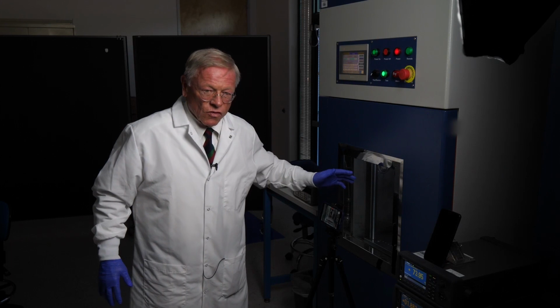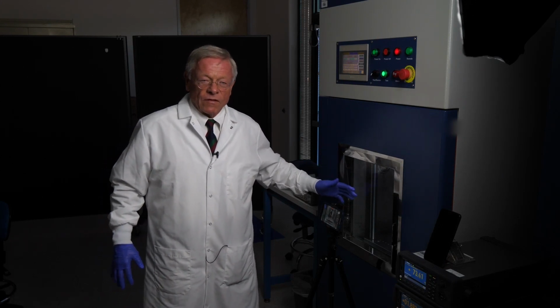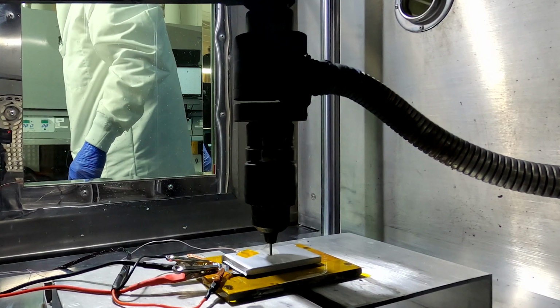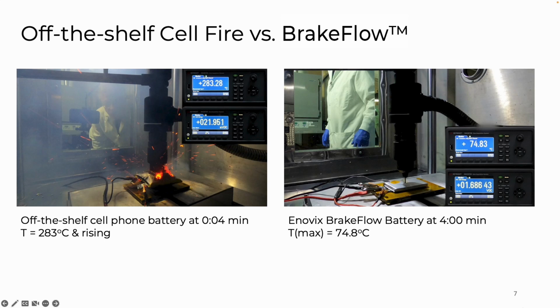This changes the danger you face if there's any catastrophic event, crushing or penetration of your battery. And this is the only technology I'm aware of that can do this. So let me summarize. The standard cell blew up in 4 seconds. It got up to 283 degrees before the thermocouple stopped working. And as you can see, it was actually splattering red-hot debris around. The BrakeFlow battery, this picture was taken in 4 minutes. It got up to a peak temperature of 75 degrees centigrade, which is 95 degrees lower than the temperature at which the separator would melt. So this is a big deal. This kind of, and I'll show you some data from outside, this hasn't happened before.